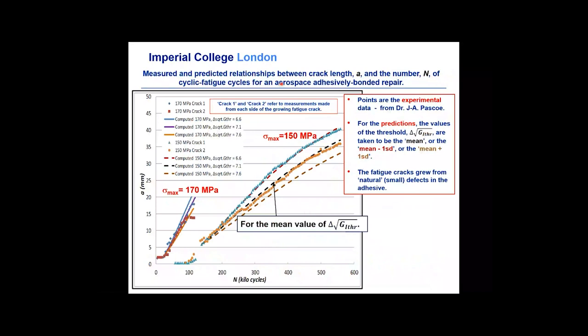Essentially, he took an aerospace adhesively bonded repair. He measured the crack length here as a function of the number of cycles. He looked at the crack from two sides, so we got two measurements from side 1 and side 2, which is a nice comparison. He did two different maximum loads in the fatigue cycle. Maybe just look at this one. It's easy to see. So there's a maximum load of 150 megapascals in the fatigue cycle. Here's how the crack is growing as a function of cycles and experiments from side 1 to side 2.